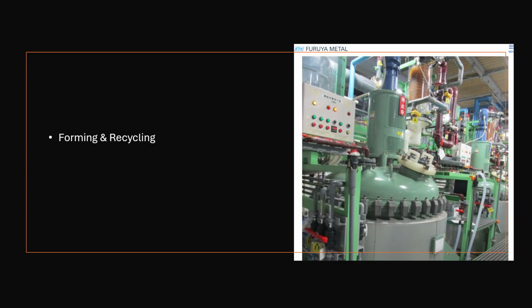After melting, ingots are processed through hot forging, rolling, or extrusion at temperatures from 1100 to 1700 degrees Celsius to form sheets, wires, or shapes. Precise temperature control prevents cracking as iridium is brittle at lower temperatures. Recycling is increasingly important, with up to 99% recovery from scrap using similar chemical and melting steps, which reduces reliance on mining.